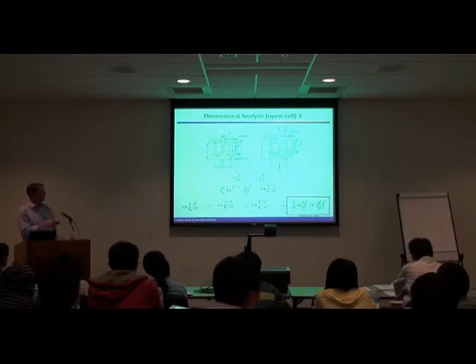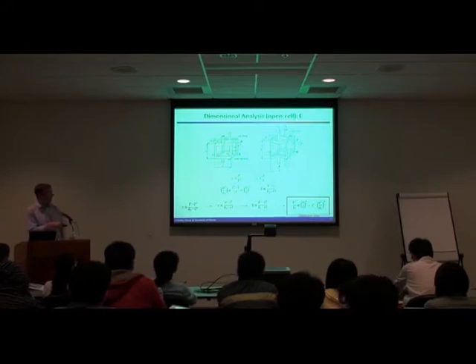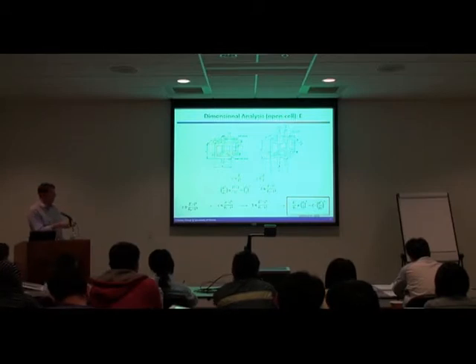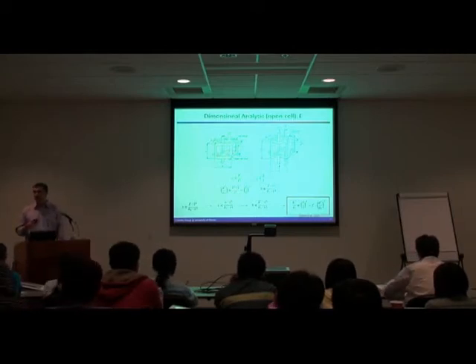So you can start to model this together, and when you combine the buckling equation with your sense of what stress and strain is within the material and the relative density, you can actually come up with a relationship between the mechanical properties of the porous foam itself and the mechanical properties of the fiber which the foam is made out of. So that's something that we might, as material scientists, be very interested in understanding. And it scales exactly as the relative density squared. So that means if you have a material that is 1% dense, and you double its density to 2% dense, you expect the modulus to quadruple, for example, because it's the relative density squared.